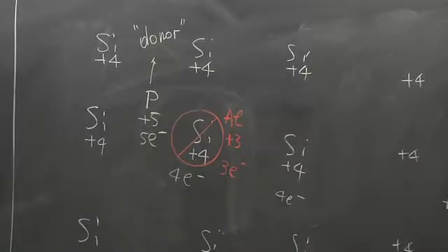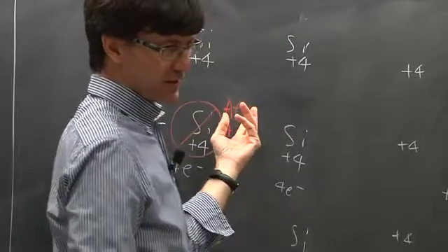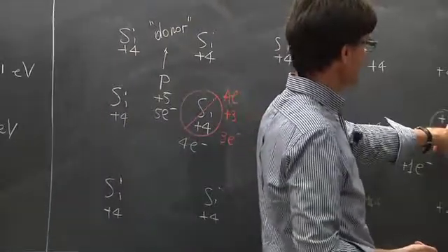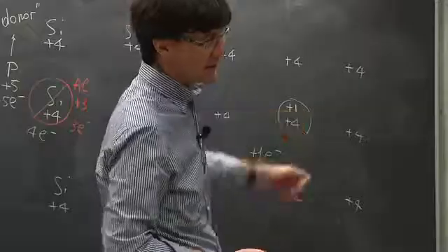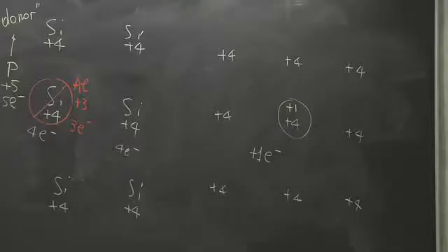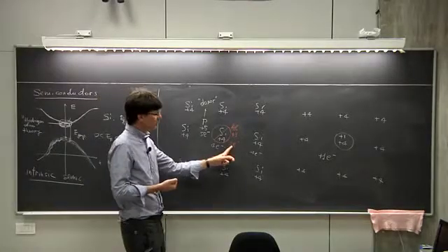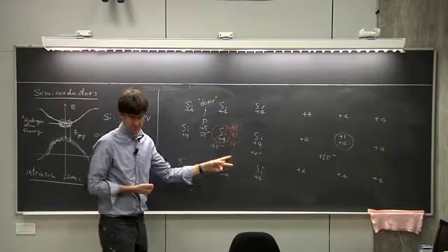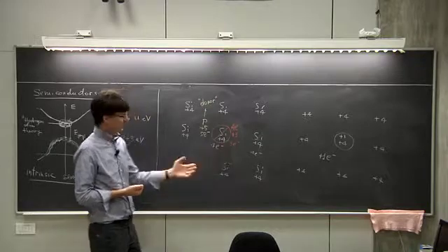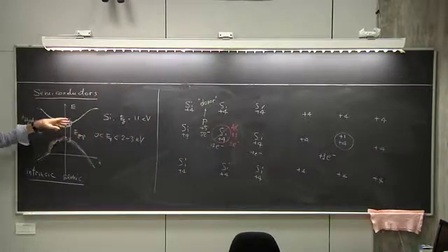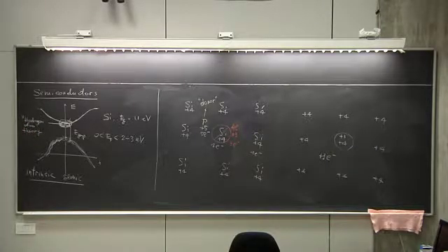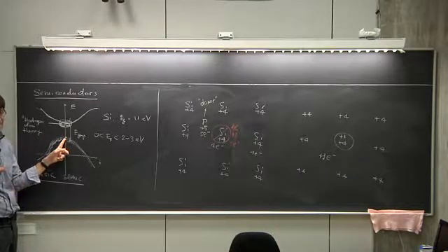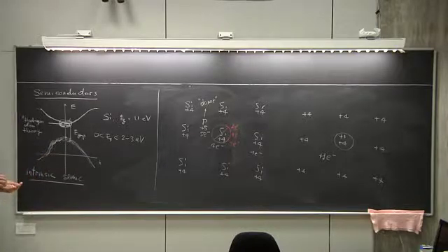What about aluminum? Well, now the argument is exactly the opposite. Instead of having a +1 charge here, I have a -1 charge that I need to add, or at least I need to remove a little bit of Coulomb attraction at that site. And at the same time, I need to remove an electron from my system, because I have to go from 4 to 3 now. As a consequence for my band structure, there will be a change in the position of the energies due to the fact that I changed slightly the Coulomb potential. Let me forget about that to first approximation. What I've done is I've removed an electron from the highest available state. So aluminum will give me an electron removed out of the top of the valence band here.